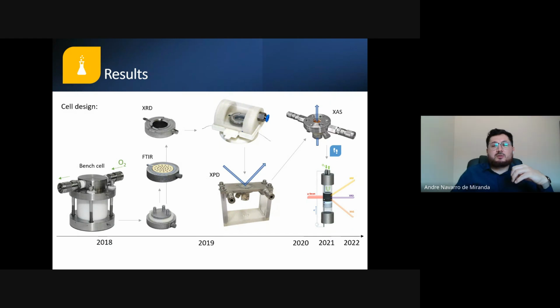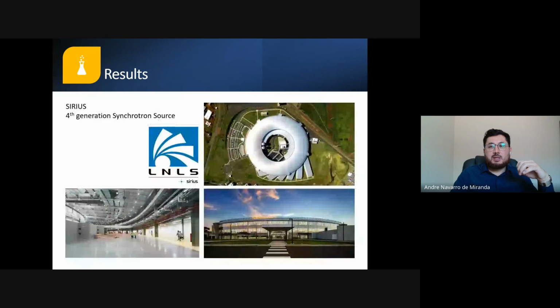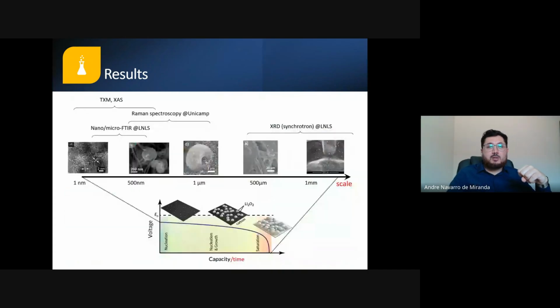To use different techniques, such as FTIR, X-rays, X-ray absorption, we change the cell design to do this analysis. I'll show you some results that we have obtained in the last 7 years. We have had a lot of help from Sirius. We submit different projects there. Sirius is a fourth generation synchrotron light source, and it's a really big microscope, and there we can understand the reaction mechanisms at an atomic or molecular level. So we have different ranges to study in the battery. We can study the film that's formed on the surface of lithium peroxide, and we also can understand the particles that are formed there during the nucleation, such as the catalysts that we use in the process.